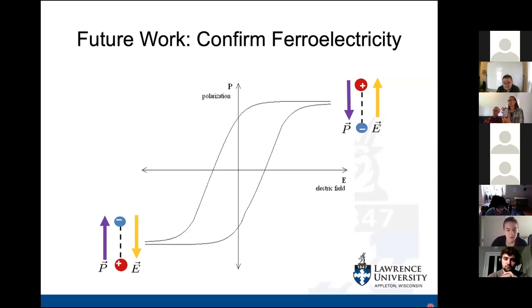This is because even though the X-ray diffraction graph suggests that the material is monoclinic due to its unique pattern, the only way to 100% confirm ferroelectricity is to produce a viable hysteresis loop by using a Sawyer-Tower circuit test. A Sawyer-Tower circuit test employs a ceramic sample of the crystal. The crystal is turned into a ceramic sample by use of a hydraulic press, which creates high pressure. The disc is situated by electrodes, and an external electric field is run through the crystal. If the material is ferroelectric, it will have the characteristic hysteresis loop created by a material with a polarization that flips from positive to negative in the presence of an external electric field.